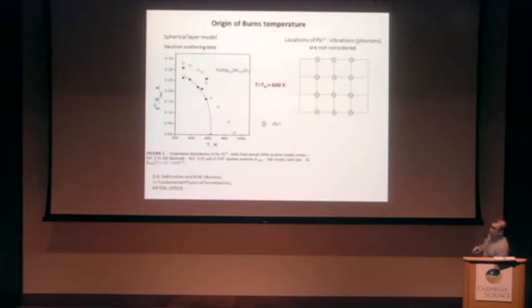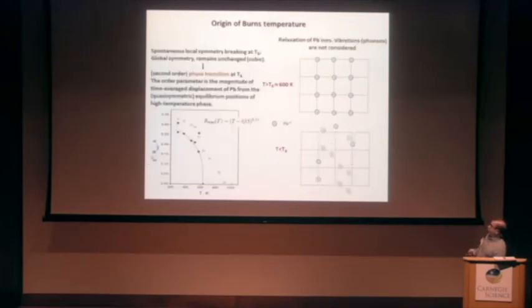But experimentally, it is not possible to determine if these displacements are static or dynamic. Thus, it could be that these are just frozen displacements of lead ions due to, for example, compositional disorder. But according to our data, we see that these are dynamic displacements of the lead cation from the centrosymmetric position, and it looks like really a phase transition from the high temperature cubic phase. And this transition is of second order, and this is the critical exponent, 0.31.